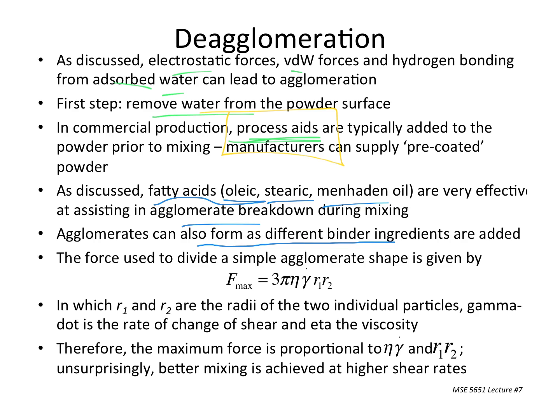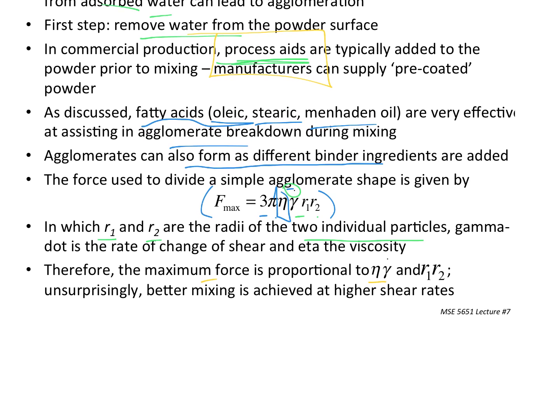ingredients are added. The force used to divide a simple agglomerate shape is given by F max being equal to 3 pi eta, the viscosity, and this gamma dot again is our shear rate. And then two things, R1 and R2, which are the radii of the two individual particles. All right. And therefore, the maximum force is proportional to, first off, eta times gamma dot. Eta and gamma dot basically being the energy we're pouring into the system and the viscosity, which is controlled by molecular weight, and then R1 and R2.